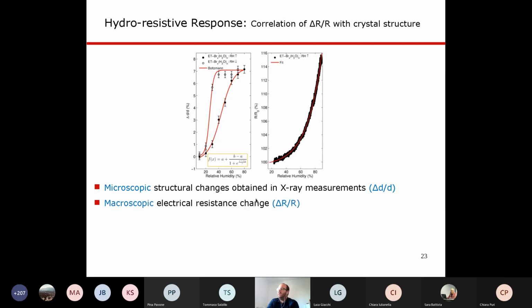While electrically, we can measure with the multimeter, for instance, at a different relative humidity, we see a different electrical resistance. And this is, for instance, the macroscopic electrical change. Now, the interesting part in this is that we can correlate these two, because it would not be very practical to carry around an X-ray machine. They are very heavy and very expensive. So this is very difficult to measure. But electrically, with a multimeter, we can measure the electrical resistance change very nicely.